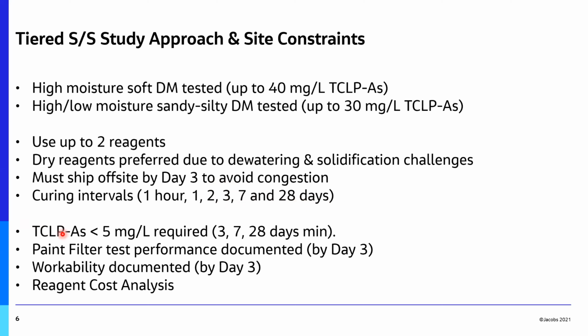So in order to be able to ship off non-haz, you need to be 5 milligrams per liter or less. That was required at all 3 of those intervals, as I indicated earlier. But the paint filter test is a test that looks at the expression of free liquids from a solidified material. So what you actually want to monitor here and take account of is traffic vibrations. This is a static test, but we've developed a test that enables you to look at the liquefaction of that material due to transport vibrations going across the road, because a lot of wastes will in fact liquefy and begin leaking when they're out on the road and be rejected at the landfill.